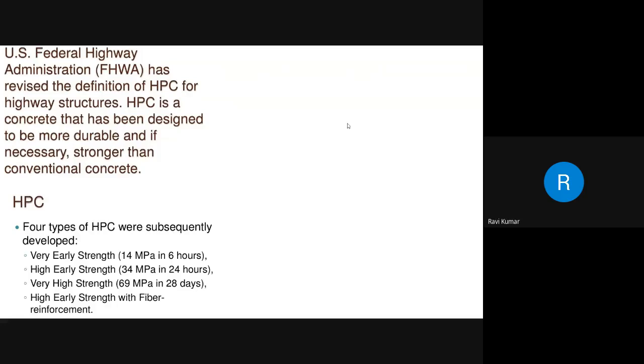So there are 4 types of HPC. One is very early strength, 14 Newton per mm square, 14 megapascals in 6 hours. High early strength, 34 megapascals in 24 hours. Very high strength, 69 megapascals in 28 days. And high early strength with fiber reinforcement.